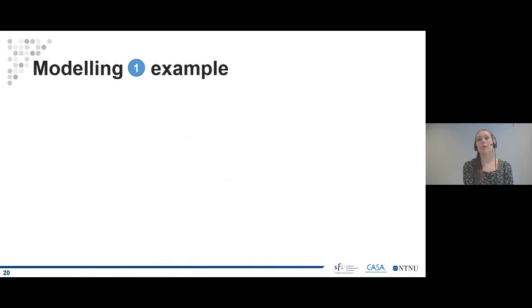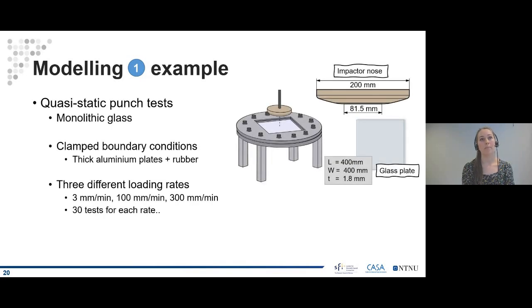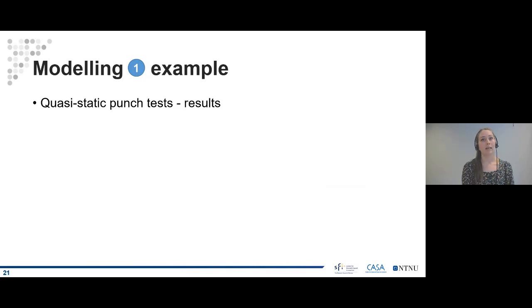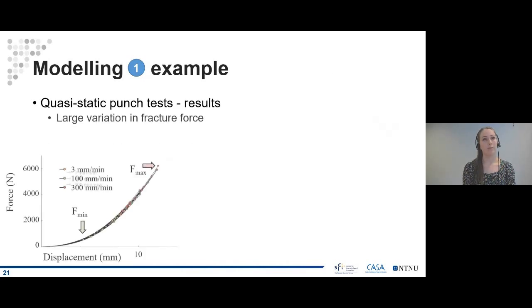All right, then I will show you an example of results from the strength prediction model. First, we did some experiments, so that we had something to compare the SPM results with. These experiments are quasi-static punch tests on monolithic glass. The glass was clamped between thick aluminum plates and rubber on each side, and the plates were loaded at three different loading rates with a flat wooden impactor, and we tested 30 plates for each loading rate. And the experimental results are as follows.